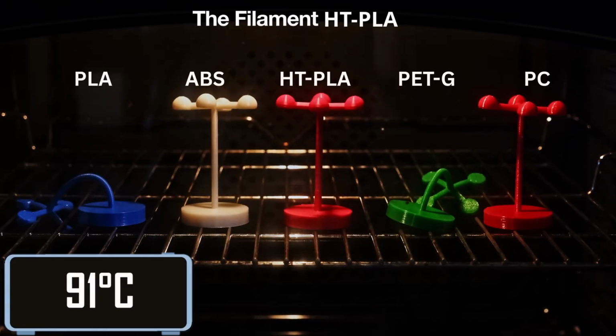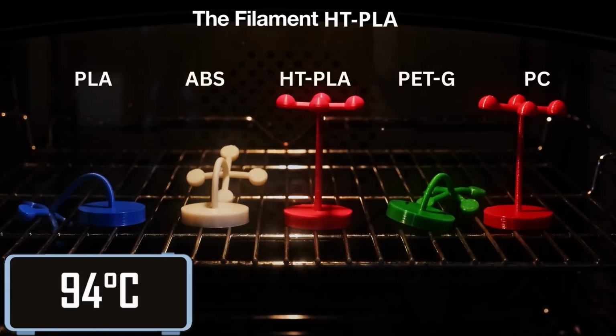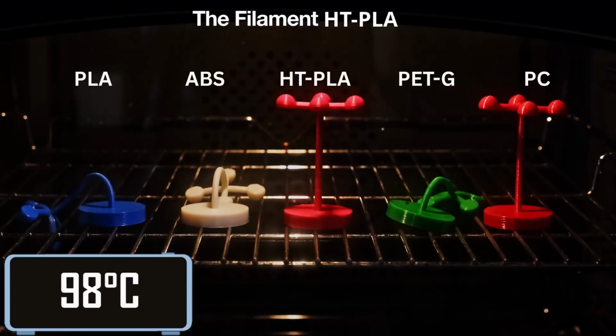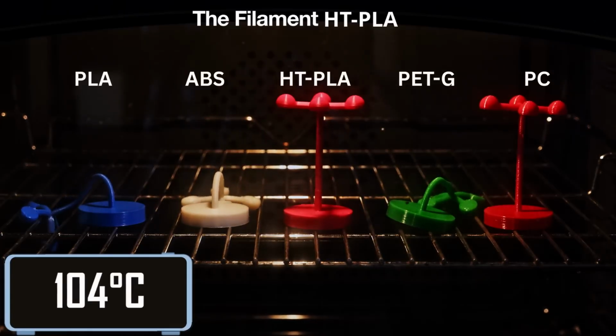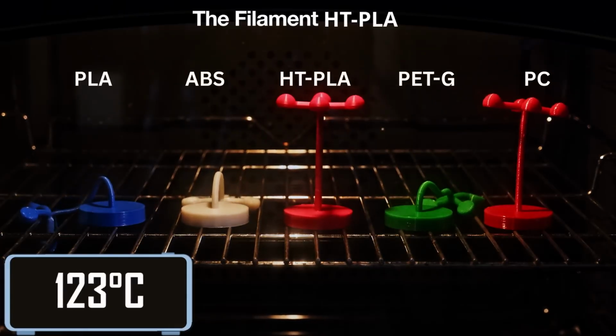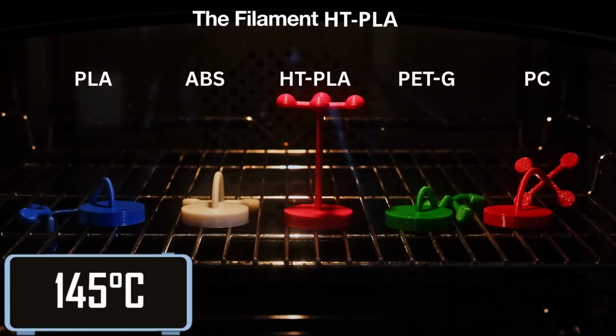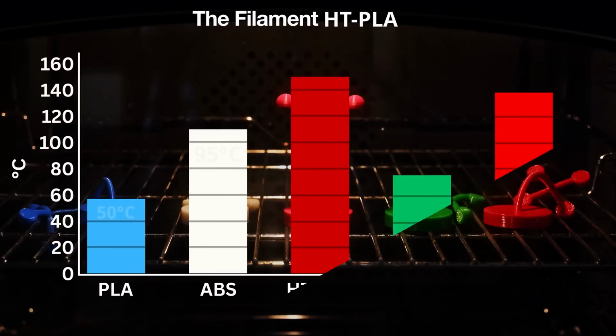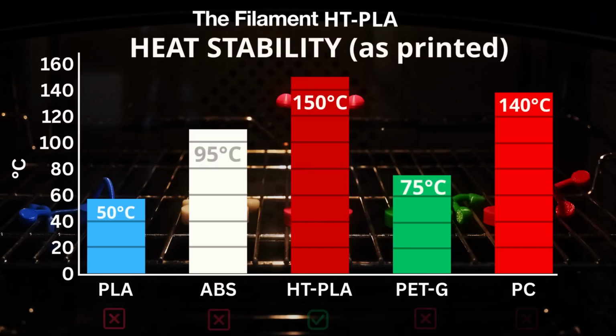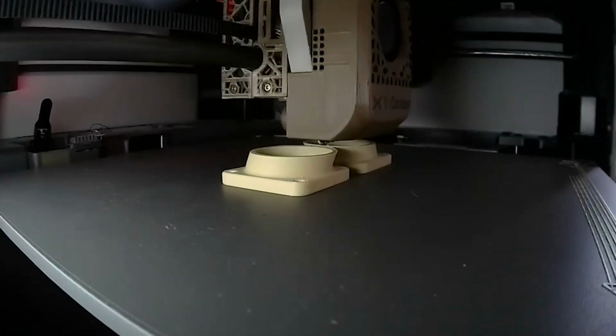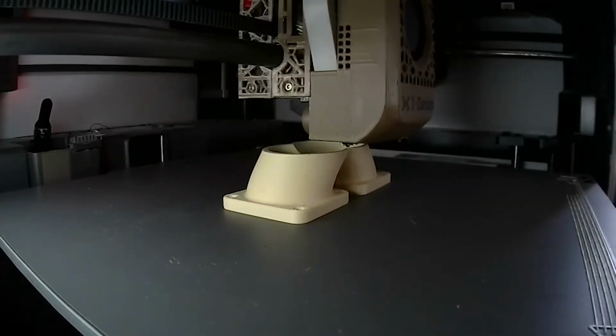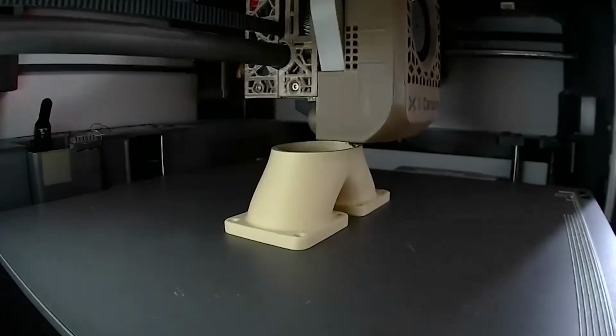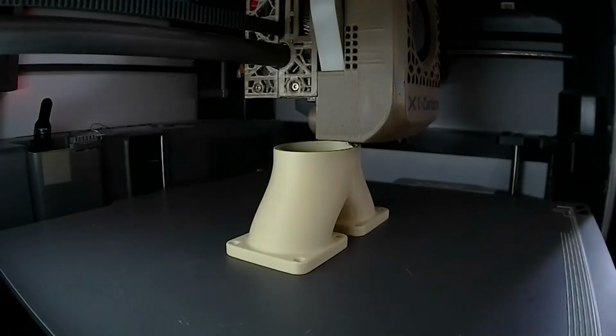Make sure the nozzle to bed distance is properly calibrated. Filament calibration is strongly recommended. For large models, it is recommended to design sacrificial surfaces to be removed later in order to minimize the risk of deformation. Bed surface and adhesion: because of the material's stiffness, HT-PLA has a tendency to slightly warp at the corners. The best results are achieved on a Bambu Lab Cool Plate Super Tack. In many cases, no additional adhesive is needed, only a bed temperature of around 35 degrees Celsius.